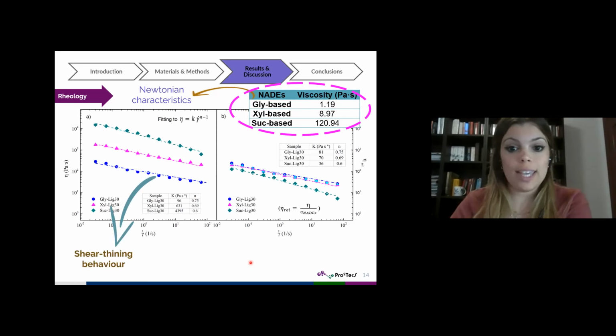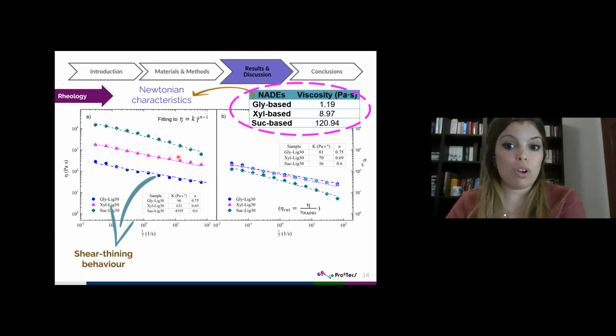On the other hand, the figure shows the viscous flow curves of lignin-structured NADES as a function of the hydrogen bond donor component. In this case, the three NADES evaluated yield highly structured shear thinning liquids, with much higher viscosity than those provided by NADES as a result of the chemical cross-linking. In this way, a power law model was used to describe the shear thinning characteristic of this formulation, where K and n are the consistency and flow indexes respectively.